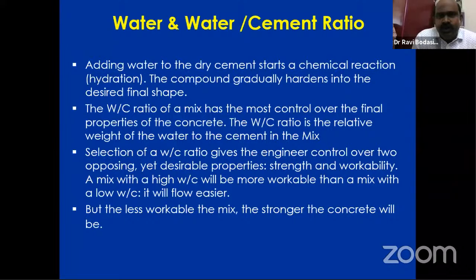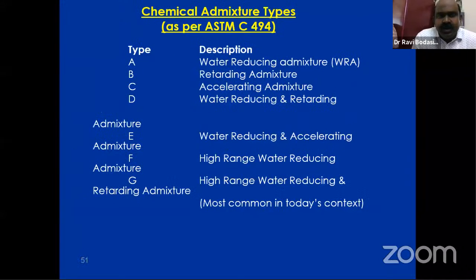We should strictly follow the codal specifications for water to attain good workability of the concrete. Chemical admixtures: a lot of companies have these types of admixtures, type A, B, C, D. Water reducing admixtures, retarding admixtures, accelerating admixtures, water reducing and retarding. Why? Because the maximum cement content per cubic meter should not cross 450 kg. That is a standard if it is pure OPC, and we can go up to 500 to 550 kg when going with blended products.